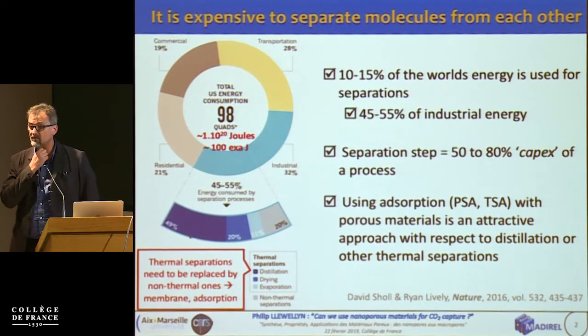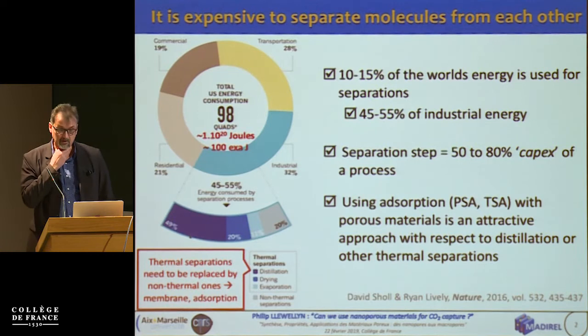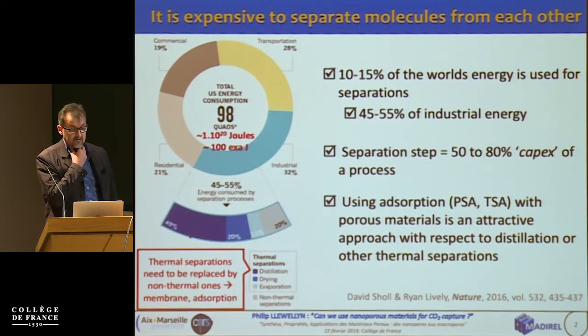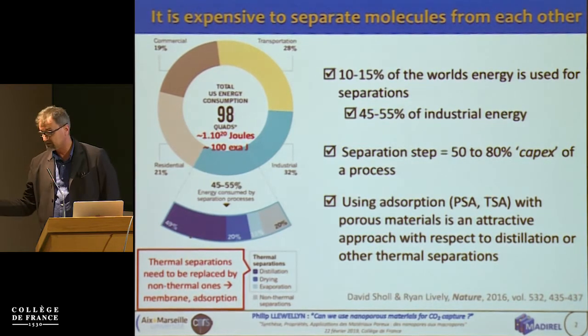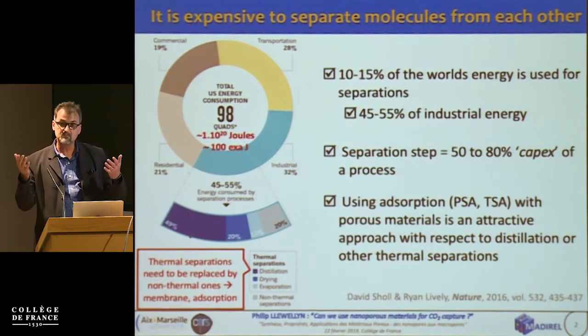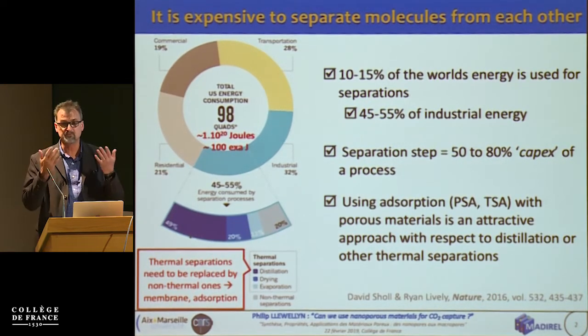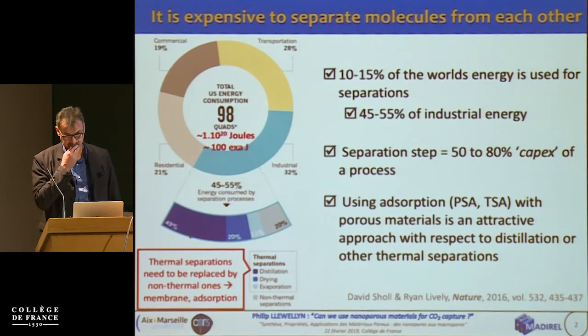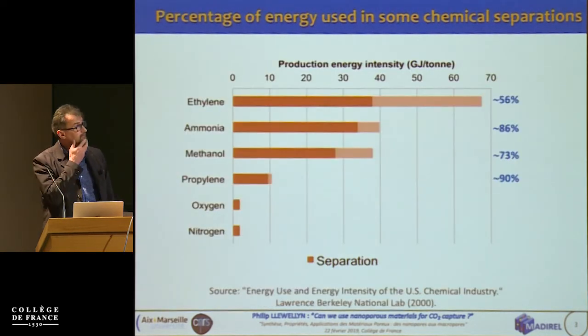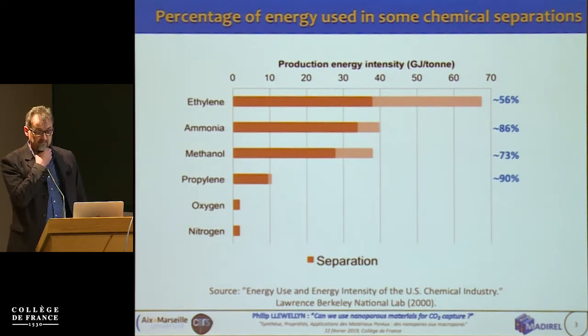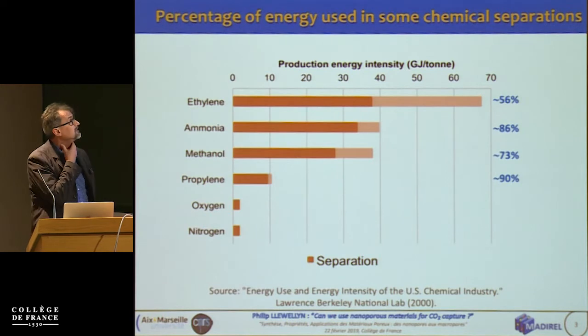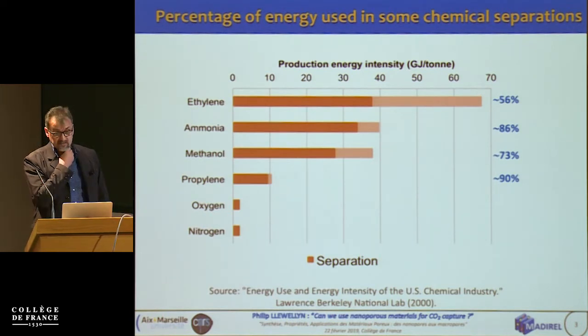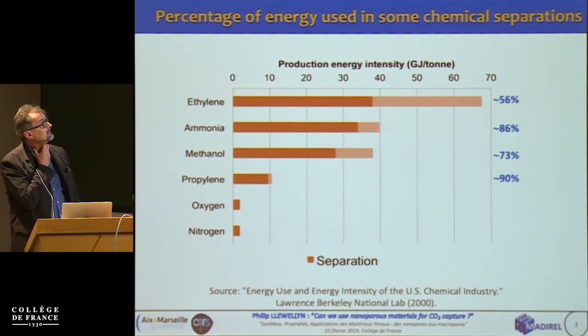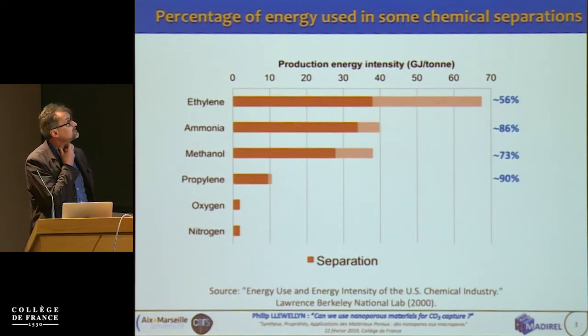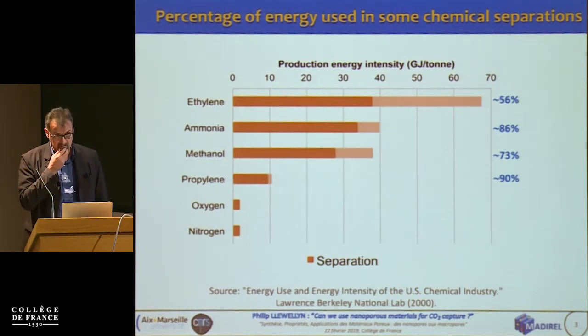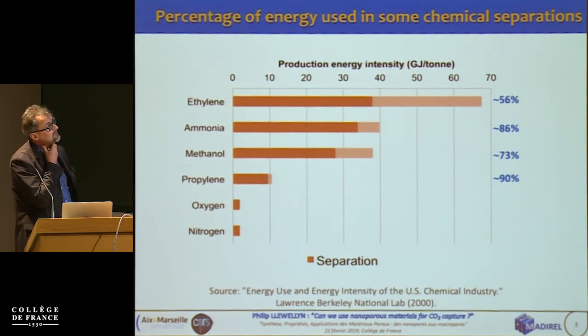So it's a huge amount of energy just used for separations of molecules. A lot of these separations are thermal separations, so distillation, cryodistillation, and these are really, really expensive. So if we can use a porous material, for example, to separate these molecules, things become much, much less expensive because we don't have to worry about too much heating the system, as you would with distillation. So just to give you an idea, these are a few gas separations. So ethylene from ethane, so ethylene for polyethylene, polymers. You've also got propylene here for polypropylene. And you can see that the actual process cost is quite large for ethylene, and of that process cost, around 60% is just due to the separation. And you have the numbers here for ammonia, for methanol, and things like this. So huge amounts of money are just used for the separations.